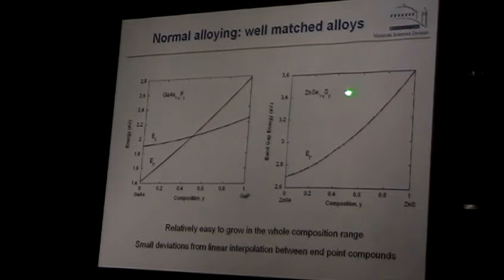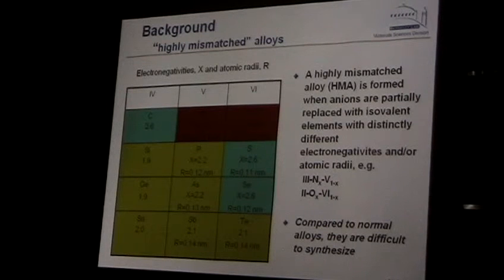You can take also a group 2-6 material like zinc sulfide selenide. Again, the energy gap in zinc selenide goes continuously in a nice manner to the band gap in zinc sulfide with small deviation from linearity. These materials are easy to grow and can be prepared easily, and the reason is that you replace very similar elements. In gallium arsenide phosphide, you replace arsenic with phosphorus. If you look at their Pauling scale electronegativity, they are the same. If you look at their atomic radii, they are very similar. So this replacement is a very small perturbation.